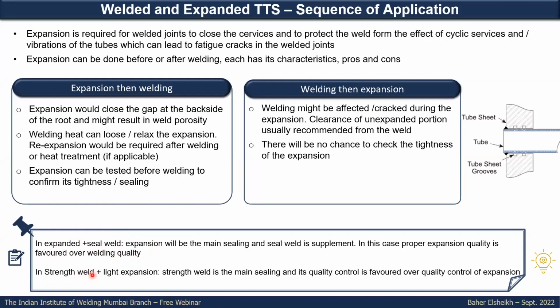In the strength weld plus light expansion, it is the opposite. Here the strength weld is the main sealing between the two sides, the tube side and the shell side. You have to think very carefully about maintaining the strength weld, more than the expansion.